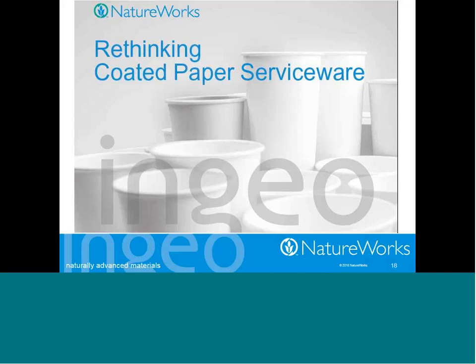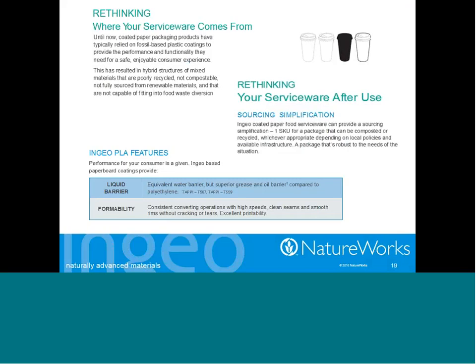So the first one is a bit on rethinking coated paper serviceware. So this is paper cups, which might not sound all that interesting, but if we rethink where your serviceware comes from and rethink where the serviceware goes after use, a typical paper cup is made out of paper and it's coated with polyethylene, and the polyethylene is there to keep the moisture from soaking into the paper and ruining the cup. Well, from a recycle point of view, that cup now is a mixed stream. It's got paper and it's got polymer, and those would need to be separated from a recycle point of view. And from a composting point of view, while the paper component is compostable, the polyolefin isn't.